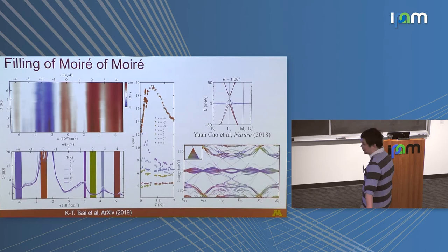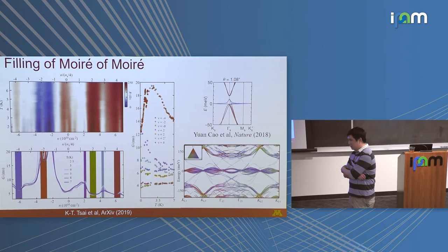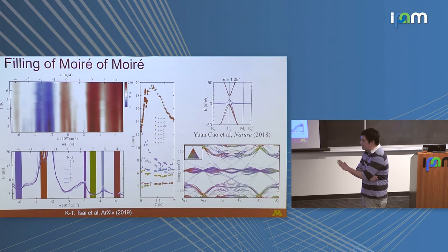the moiré unit cell. You can extract from the peak position, in terms of density, the angle, to be about 1.1. That's exactly what we're trying to hit. Extremely low density. Do you think you have accurate mechanical control over that? Yes, I'll show you. Not accurate in the sense of plus or minus 0.2 degree, which is consistent with, and slightly bigger than, what people can do with a twisted bilayer.